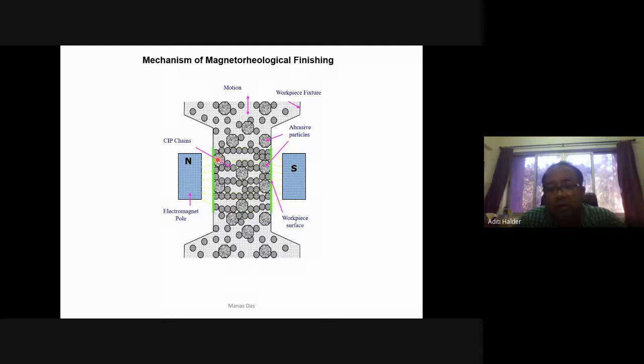Alumina is the lowest one, then silicon carbide, then boron carbide, and diamond abrasive is the highest available ceramic abrasive particle. These ferromagnetic iron particles are 99.99% pure iron particles. These are soft iron particles. So these iron particles do not take part in the material removal. Only the abrasive particles which are mixed with these iron particles take part in the material removal.